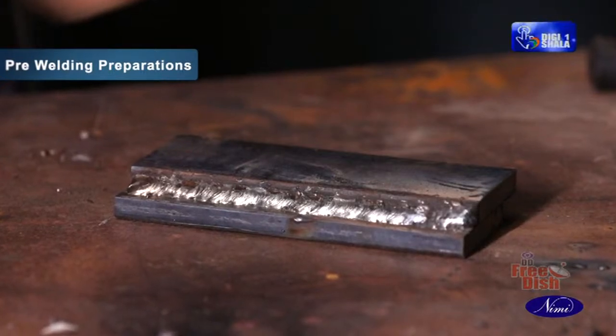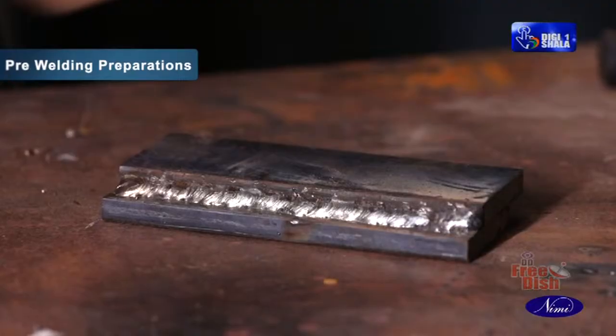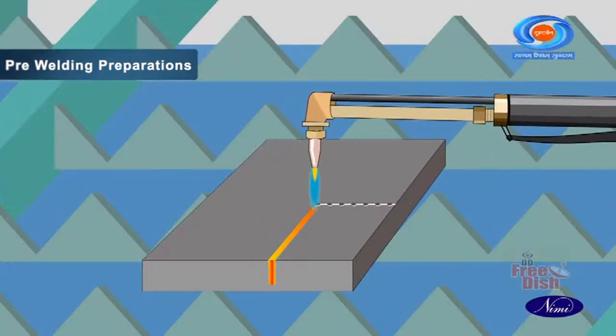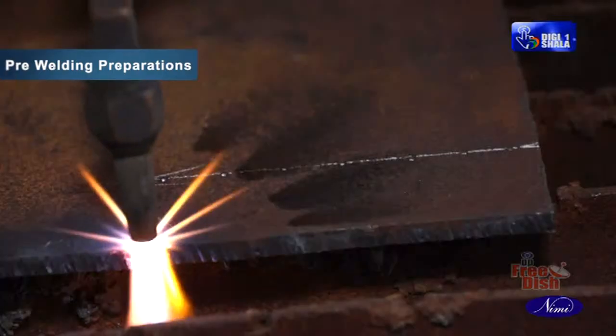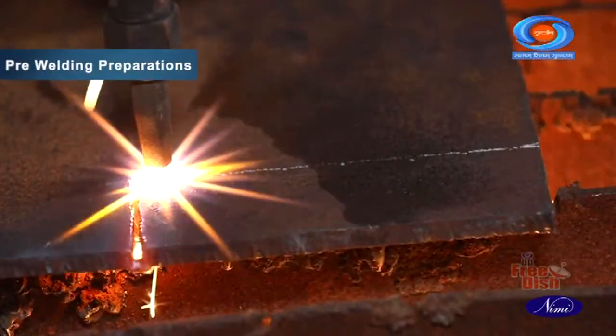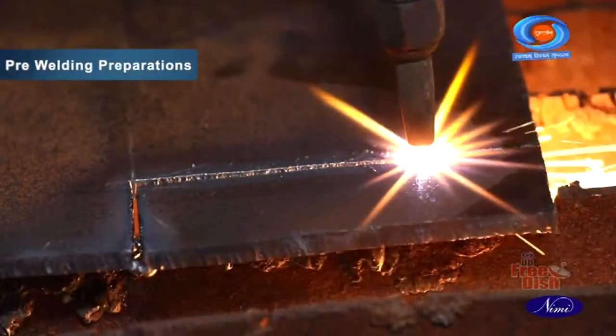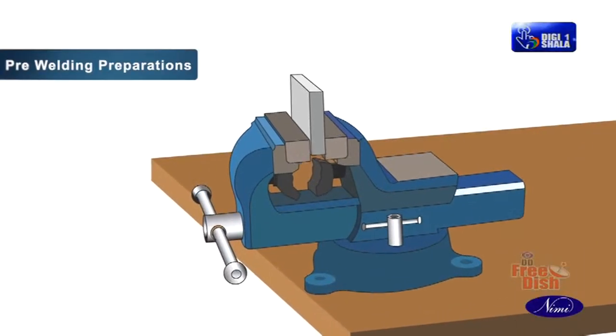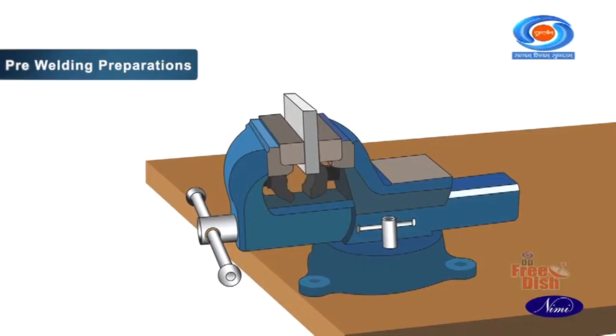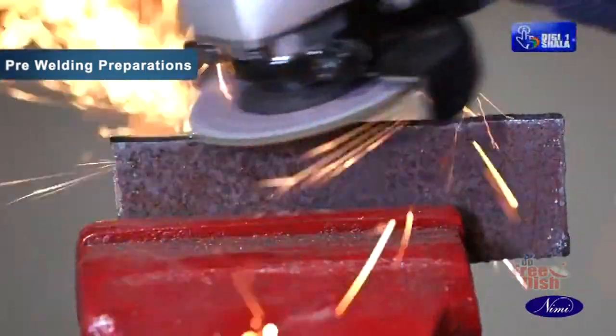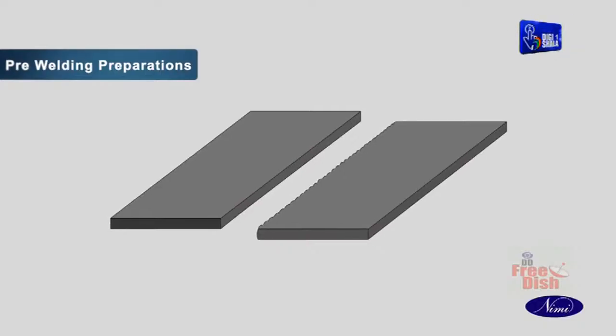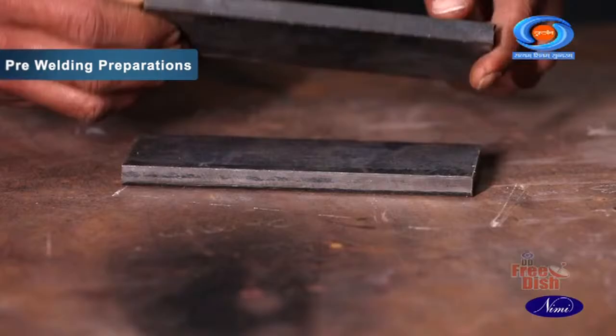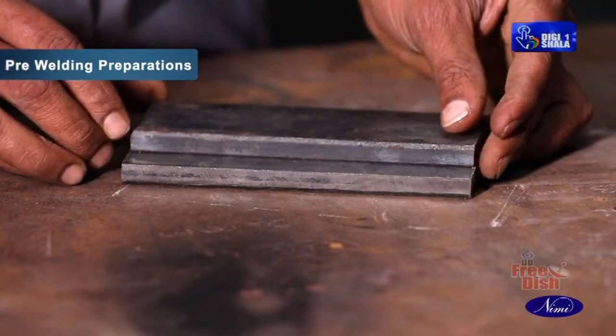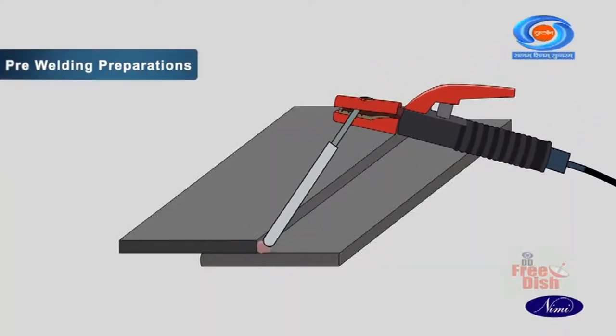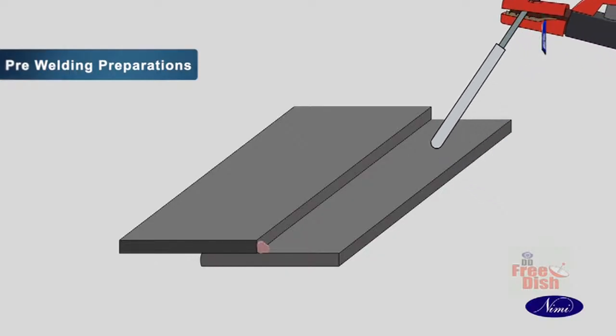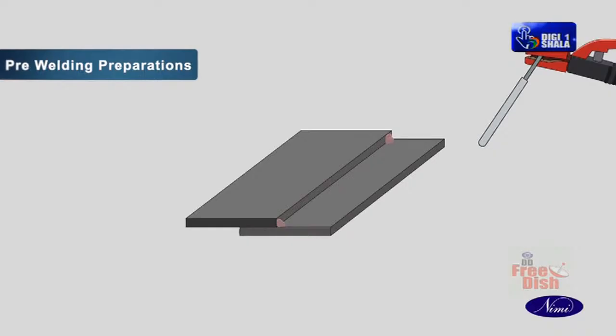Now let us see the procedure for the fillet lap weld by the SMAW process. Cut the plate pieces by gas cutting and grind the plate edges to square. Remove the grinding burrs and clean the surfaces. Set the pieces in the form of a lap joint as shown. Tack weld on both ends and ensure the two lapping surfaces are perfectly cleaned and contact each other properly.